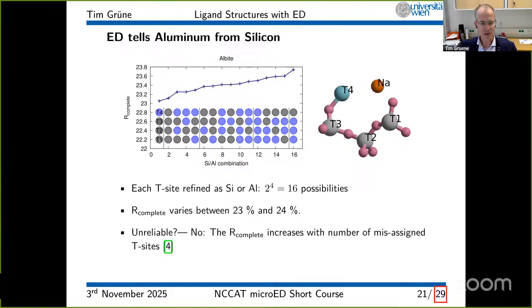And what we did in this structure, we collected data from a couple of crystals, and then we refined them, and we refined each T site either by silicon or by aluminum. With this, we have 16 different possibilities of combinations. So you see the chart here, and each row is for one of the T sites. In the last column, we modeled everything totally wrong. So every T site that should be a silicon was modeled as aluminum, that's blue, and the one that should be an aluminum was modeled as a silicon.